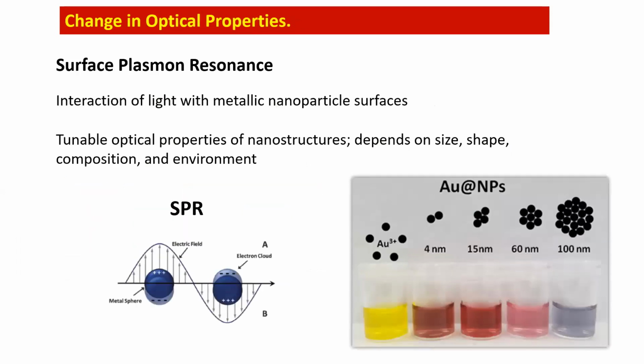Another very good application of this nanomaterial is especially in noble nanoparticles. The noble metals are silver, gold, copper. These materials are very interesting because they have an electron cloud. There is no band gap type of thing. There is an electron cloud at the surface of the material, and that electron cloud can easily react with the incident light, that is the sunlight, and it can generate resonance at a particular wavelength based on its size.